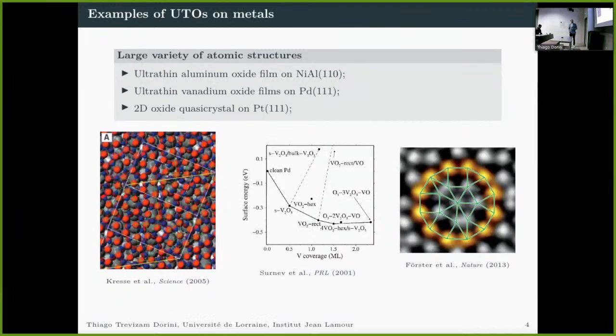And here I'd like to highlight some of the famous examples of these phases. The first is aluminum ultra-thin oxide film deposited on nickel aluminum 110, as you can see on the first image on the left. So it's interesting to notice that the structure of this phase changes completely from the bulk material. And this happens for many, many cases. This happens also for this ultra-thin vanadium oxide when supported on palladium 111, that the structure of these oxides also changes considerably when you change the vanadium coverage on these oxide films. And lastly, what I show you here is the first discovered 2D oxide quasi-crystal when supported on platinum 111, which was discovered by the group of Dr. Forster in 2013. And I'll be discussing in more detail this structure later on in this presentation.